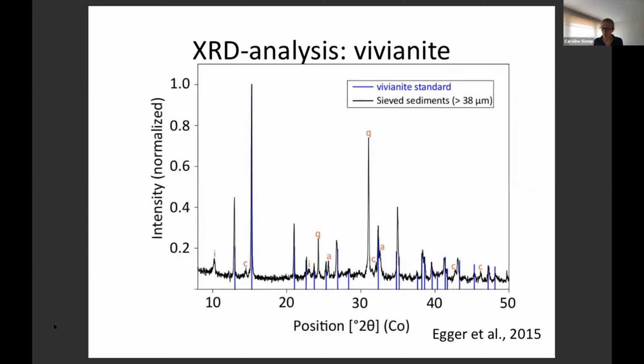Next slide, please. What you then can do is you can take a lot of these crystals that you've sieved, you can take that fraction and do XRD with it. And so that's what we did here. And if you then look at this, you can actually see that this is indeed Vivianite. You can compare it to a Vivianite standard. And in fact, what we saw from this is that this is a manganese-bearing Vivianite. Next slide, please.